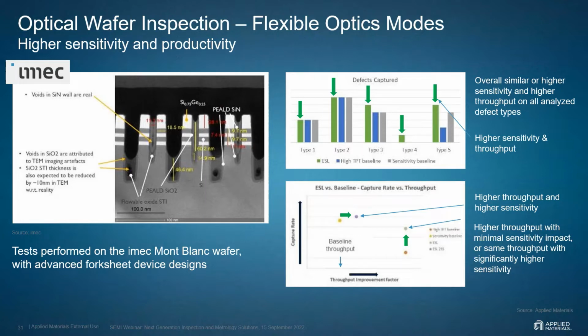The green indicates the new modes, and you can see that the green is performing better on type 4 and number 5. And on the bottom, we can see that not only were we doing better in terms of detection, we also managed to improve the throughput of the detection on these defects. So overall, we have a higher sensitivity and higher productivity.